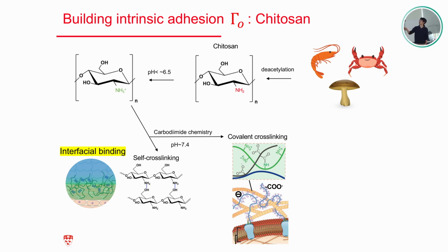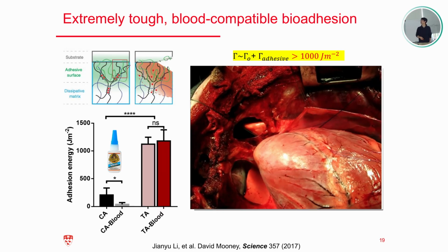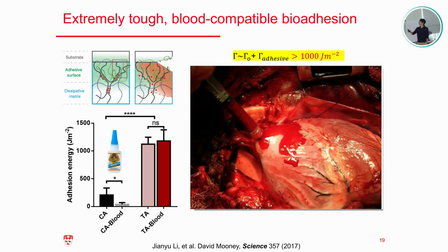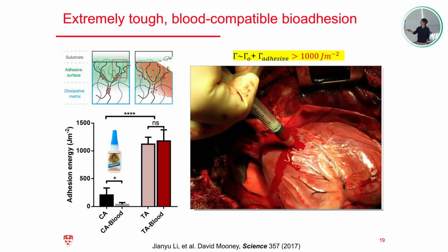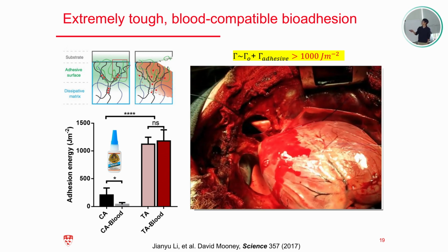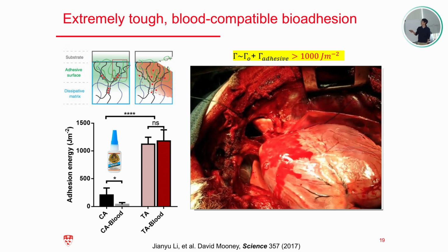So that allows this polymer to self-cross-link. Without adding UV light or heat, just by tuning the pH to neutral, it can form a bridging network at the interface, which will maximize the interaction between the adhesive and the tissue substrate. I apologize for a bit of a bloody video here, but I just want to show you the case of